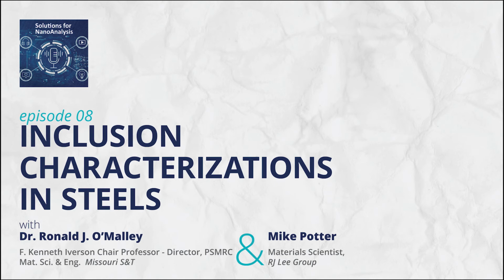If we look at one population that is a solid distribution of oxides, predominantly pure alumina or any other solid inclusion, and we compare it to an inclusion that has been modified, say, by calcium treatment, where it's converted into a liquid inclusion, we find that the solid inclusions interact strongly and are removed much more efficiently than the liquid inclusions. So what this says is there is a preferred path by which you do rinse stirs in the steelmaking process to remove oxides. Was that a surprising finding?